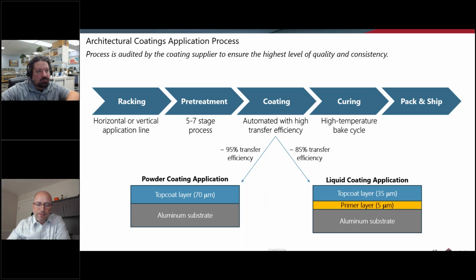Now, when you look at the differences between the two pictures down at the bottom, for powder coating application, usually your top coat is going to be around 70 microns. It varies pretty widely, but on average, 70 microns is a decent number for the average film thickness. You'll notice that there's no primer used on powder, and that's generally the case.